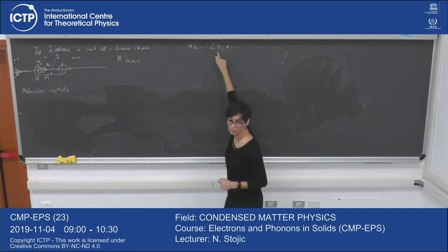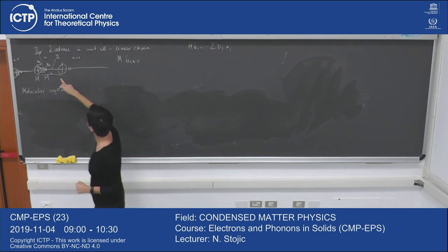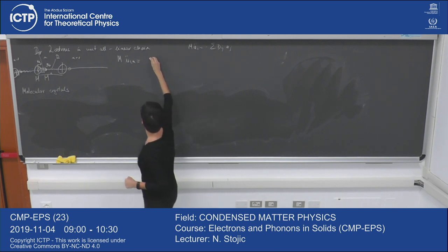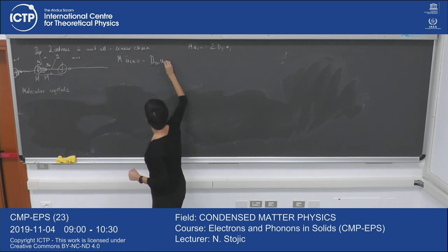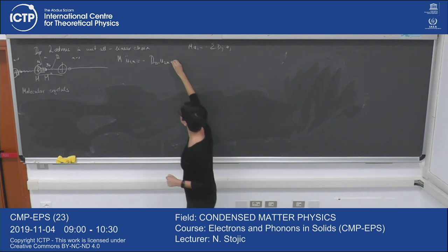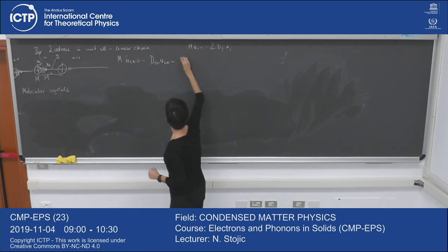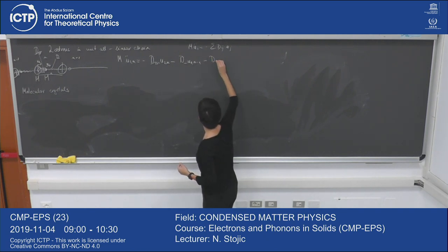We have to make a sum of all the neighbors of these force constants. So what do I have here? U1, atom 1, the first neighbor is atom 2 in the same cell. So it will be minus D, the spring is strong one, U2N. We're in 1D, so no vectors. Minus D, weak is connecting to the N minus 1 cell, U1, N minus 1, and then there is its own D0, U1, N.